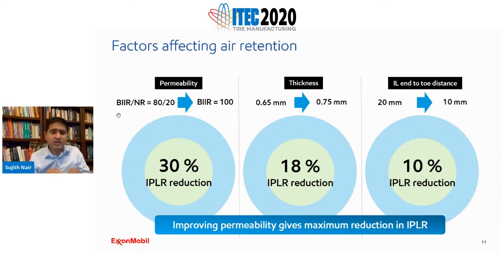30%. The inflation pressure loss reduction, or IPLR, is a terminology used to measure the air retention performance of a tire. What it means is the percentage of air lost from a tire in a month. That's basically what the IPLR is. So the lower the IPLR, the better the performance. We have seen that if you just go from a composition of 80-20 bromobutyl natural rubber to 100% bromobutyl, there is a 30% reduction in IPLR, which is very significant.